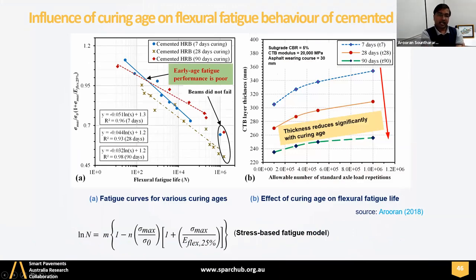So based on this experimental result, we have come up with a stress-based fatigue model, which I explained. Don't worry about this jargon here. Essentially, this is sigma versus N, stress versus number of load cycles, the fatigue curve in cementitious materials. And what I have done during my PhD is develop this fatigue curve for different curing ages, 7 day, 28 day, and 90 day. That means the cemented base beam prepared was cured for 7, 28, and 90 days, and then it was tested in the four-point bending apparatus, and the fatigue performance was analyzed.